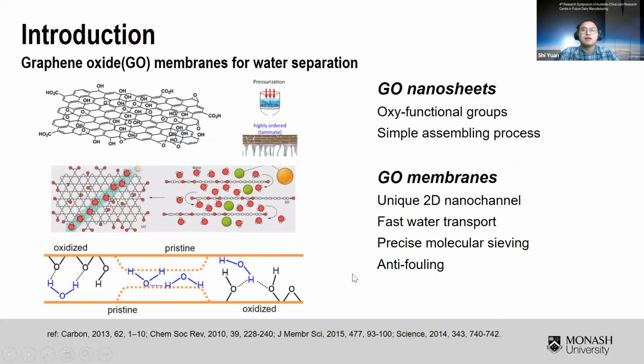With the emergence of graphene oxide, graphene-based two-dimensional materials have drawn a lot of attention. Particularly graphene oxide, as mentioned by Yang before, can be easily fabricated in aqueous reaction and has been used to prepare high-performance membranes. Graphene oxide nanosheets contain abundant oxygen functional groups, and they can be feasibly assembled into membranes by vacuum filtration, spin coating, or solvent evaporation. These graphene oxide membranes exhibit unique 2D structures, which allow fast water transport as well as precise molecular sieving. And due to the good hydrophilicity of GO-based membranes, they also show good anti-fouling ability.